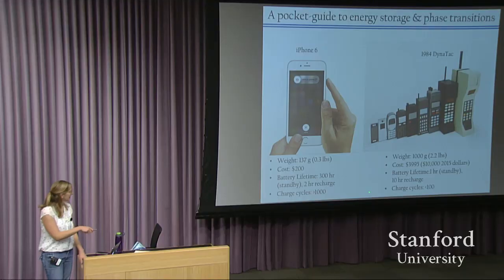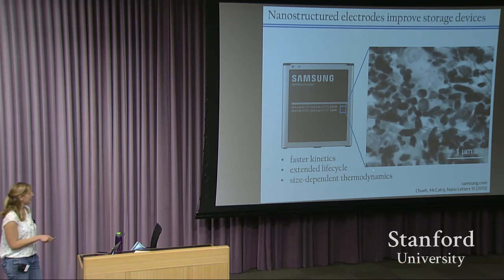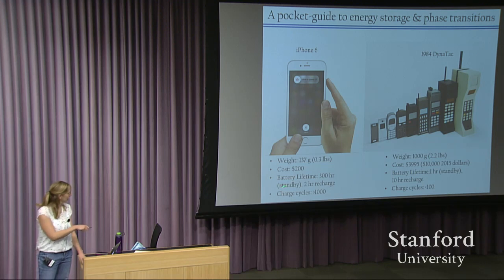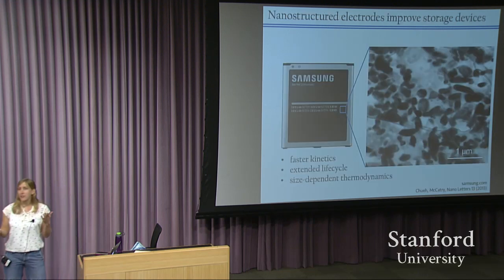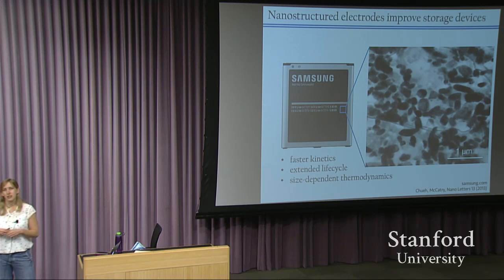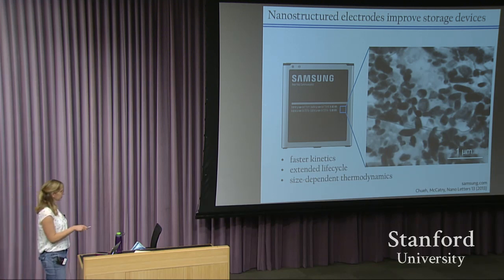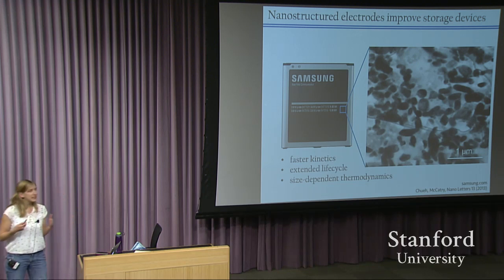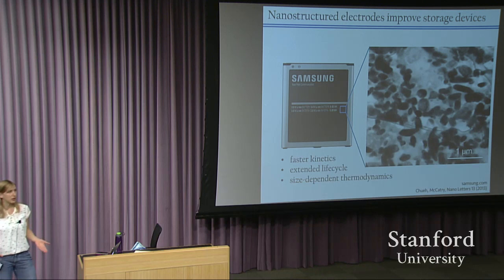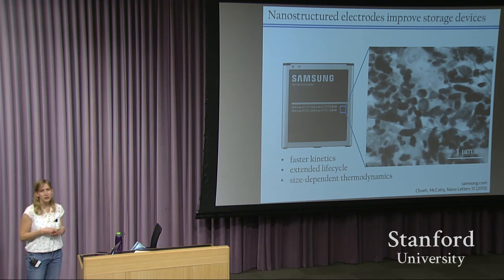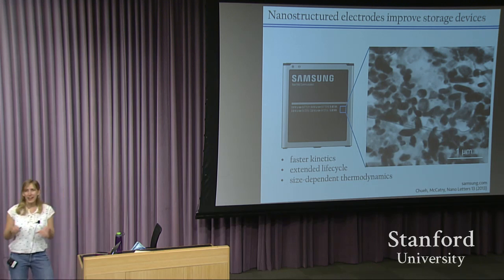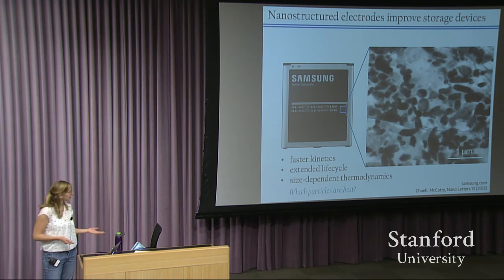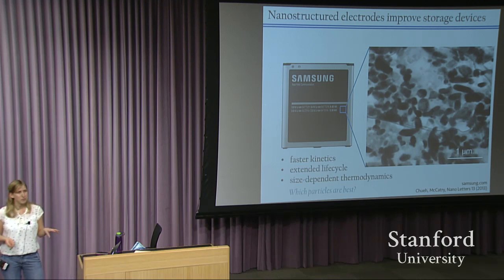So just going back to this slide, now you can see basically it only takes about 2 hours to recharge a battery instead of 10 hours. Further, it's been found that they have an extended life cycle. So again, going back to this slide where we have 1,000 charge cycles on our iPhone now compared to less than 100 charge cycles back in 1984. It's been found that if you nanostructure the electrodes, you can charge and discharge your battery many more times before it needs to be replaced. And then finally, it's been found that these nanoparticles tend to have size-dependent thermodynamics. So for example, you could charge up your battery at a lower potential, a lower chemical potential, if you nanostructure your electrode. But looking at this picture, you'll notice that there are nanoparticles of a variety of sizes and shapes and crystallinity. And it's not really clear which particles are best. And that's part of what my talk is going to address today.